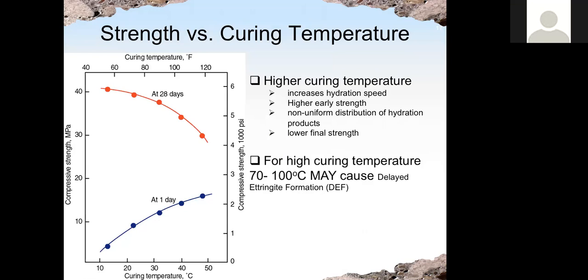Here shows how the curing temperature affects the strength at 1 day, which is the blue line, and also at 28 days. So similar to the traditional curing temperature, if we increase the curing temperature, the early day strength will be higher, but the 28 day strength will be lower. Okay, again, for the same reason. Higher curing temperature will increase the hydration speed, so we have higher early strength. But it will also generate non-uniform distribution of hydration product, and that will result in lower final strength.